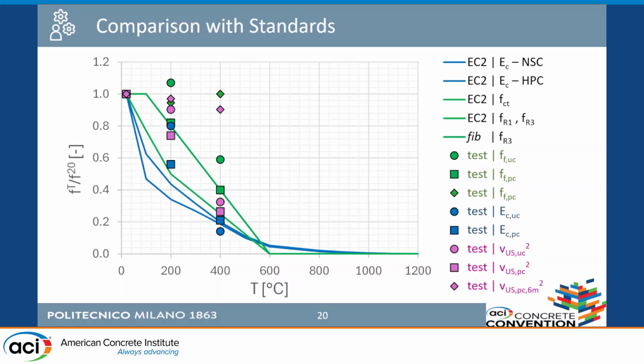But if we move to the rhombus that are here and here, we see that we have almost a total recovery of the properties. And this is true just for the flexural strength, because if we move to the Young modulus, okay, here I did not represent the recovery, so there are no blue rhombus. But I would like to show you that at 400 degrees C, we are on the line derived from the Eurocode. But at 200 degrees C, we are far higher, without self-healing. Because this test, circle and square, refers to the test just after the heating.